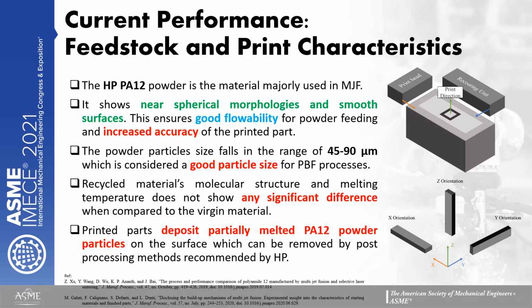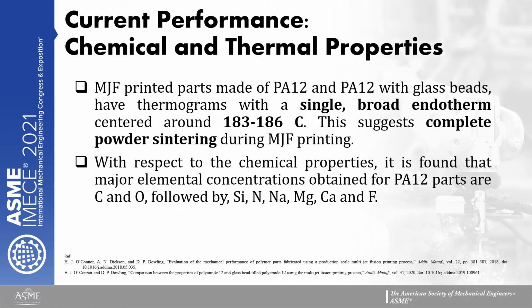Recycled material's molecular structure and melting temperature do not show any significant difference when compared to the virgin material. Printed parts have partially melted PA12 powder particles deposited on the surface, which can be removed by post-processing methods recommended by HP. The chemical and thermal properties: multi-jet fusion printed parts made of PA12 and PA12 with glass beads have thermograms with a single broad endotherm centered around 183 to 186 degrees Celsius. This suggests complete powder sintering during multi-jet fusion printing.